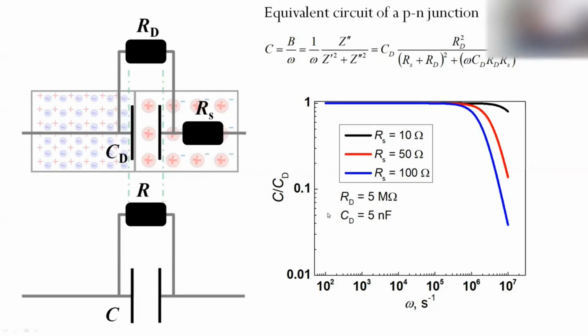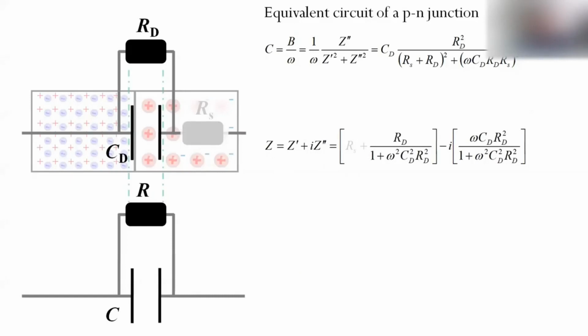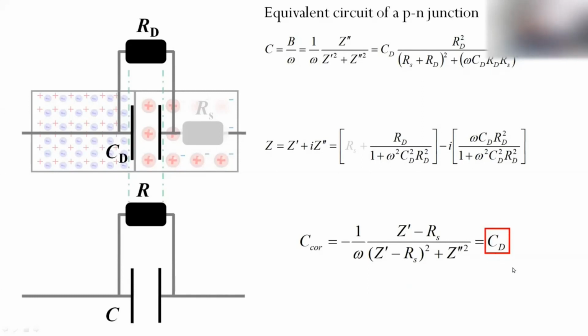That's why if we use this measured capacitance in the mentioned Mott-Schottky relationship, we will get just the wrong concentration of doping molecules, and that will be a misinterpretation of experimental data. However, with impedance spectroscopy, we can easily subtract the series resistance from the real component of impedance. So we measure this real component, we subtract series resistance, and then when we substitute these expressions for Z prime and Z double prime, we can get the depletion layer capacitance directly. So we will get exactly that characteristic which is necessary to do correct analysis.